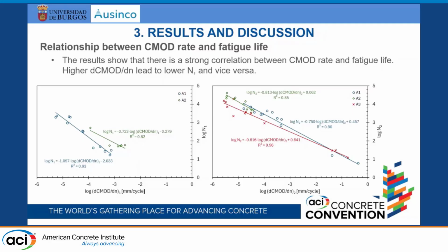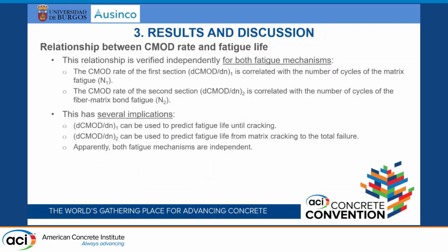So what is the implication of that? The implication is that if we know the CMOD rate of the matrix fatigue, the first part, we can predict the fatigue life until cracking, just until cracking. And if we know the CMOD rate of the second part, we can predict the fatigue life from the matrix cracking to the final failure of the specimens. So apparently, these two mechanisms are independent, but each one has a CMOD rate that is able to predict, or correlates really nicely with, the number of cycles.